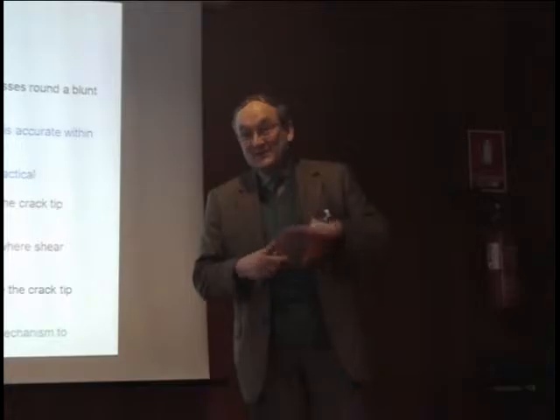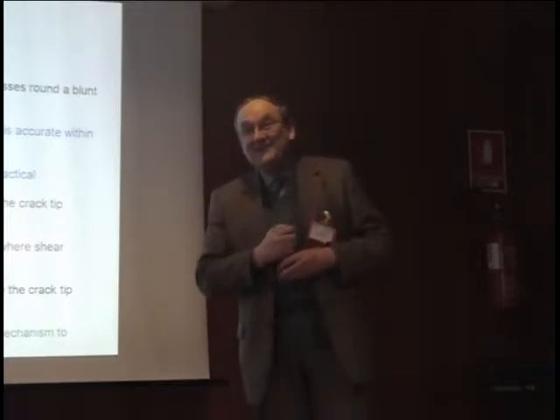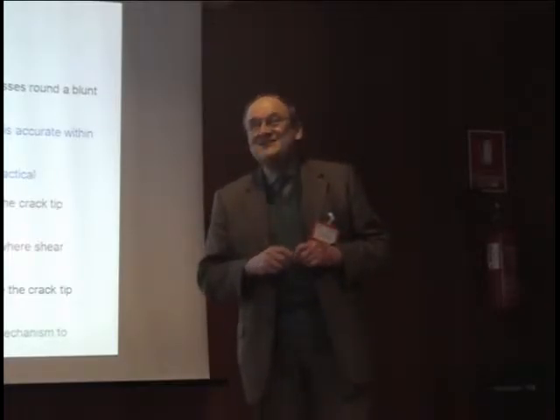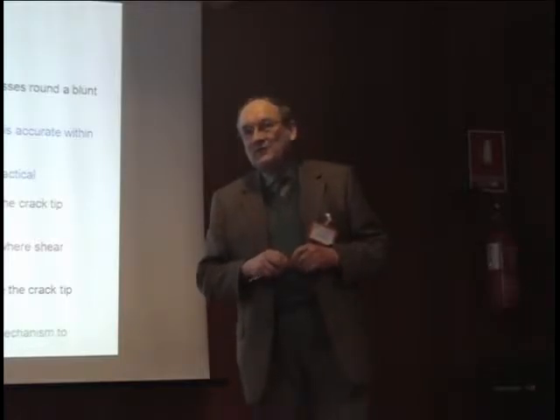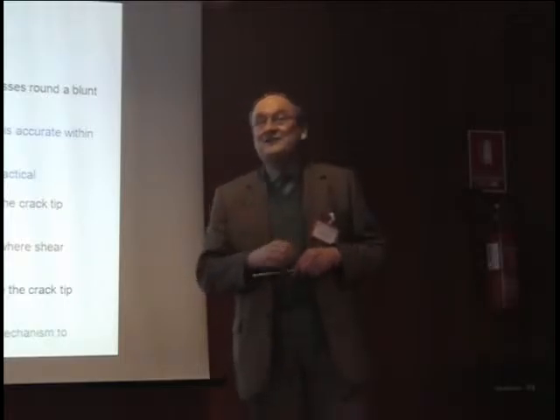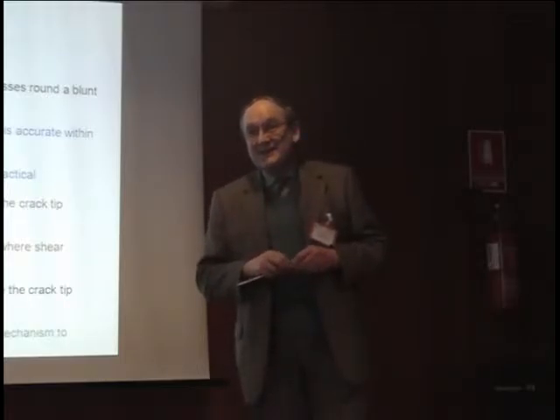Well, certainly for a tubular cyclic torsion, that is a shear plane. Yes. So without the crack there, it's a nice case of reverse shear. We're just putting the crack on what should be a shear direction. And certainly in low cycle fatigue, we do get nice shear cracking in that direction. To be fair, in low cycle fatigue, it's usually a three-dimensional crack. It's also got mode 3 around to help stabilize things.